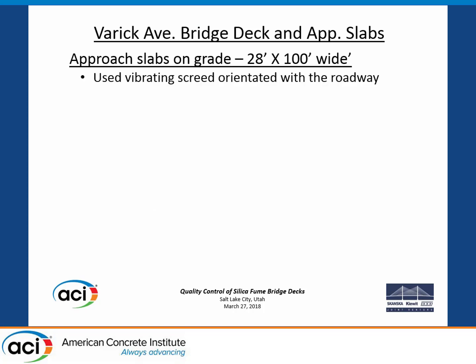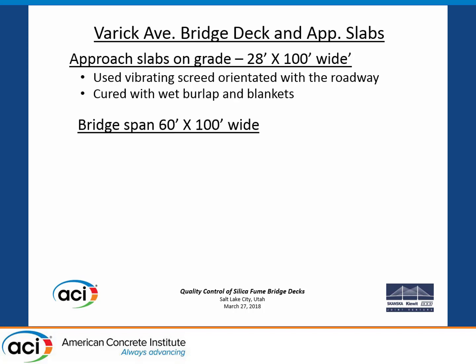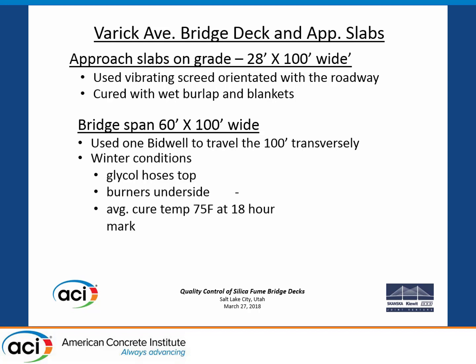Okay, slabs on grade. We used a vibrating screed on the approach slabs. We cured it with wet burlap and blankets. The bridge span we used is 60 by 100 wide. We used 1 Bidwell to travel 100 feet back and forth. Just 1 Bidwell carriage. Winter conditions, we put glycol hoses on the top. We put burners under it, and the average concrete temperature was about 75 degrees at the 18-hour mark.